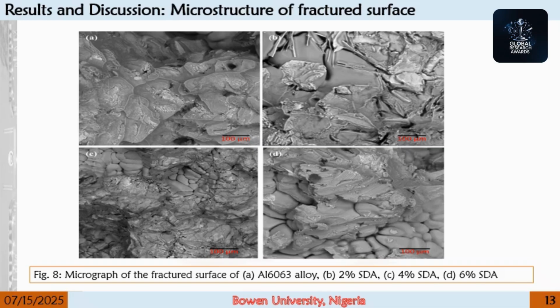And the reinforcement particles have the tendency of reducing the crack propagation due to the material flow restriction, according to Yadav and Bowen 2011. Also, SDA addition enhances the plastic deformation of the composite, while the elastic deformation is reduced with increased load of composite. Better compatibility as SDA content increased in the matrix alloy. This could be linked to the increased hardness and tensile strength values of the composite.